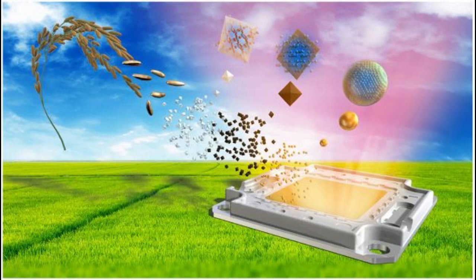The LEDs were assembled as a series of material layers. An indium-tin oxide glass substrate was the LED anode. It is a good conductor of electricity while sufficiently transparent for light emission. Additional layers were spin-coated onto the ITO glass, including the layers of silicon quantum dots. The material was capped with an aluminum film cathode.